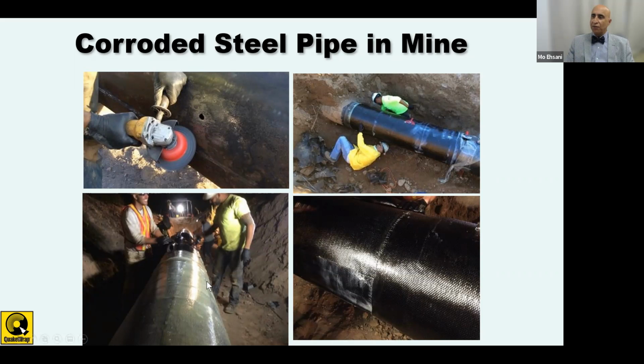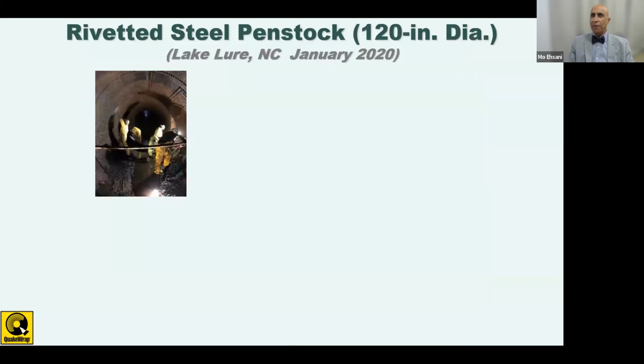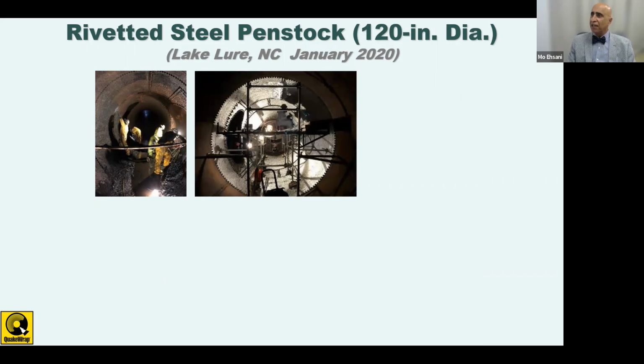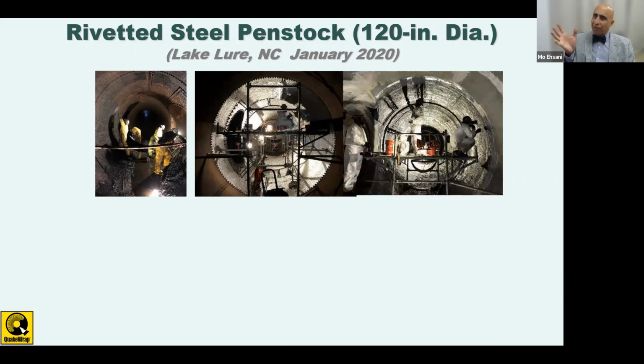In this case, the first layer of glass has been applied, and it looks like it took 2 layers of carbon fabric to achieve the pressure rating that we wanted. These can be done, we are doing these for water, oil, gas. They can be done, as I mentioned, on the inside or outside of the pipe. On the inside of the pipe, for example, this is for a penstock. We have done a number of these penstock repairs worldwide, but these are usually at this time 80, 90 years old. This happens to be a riveted penstock in North Carolina. So a couple of things to point out.